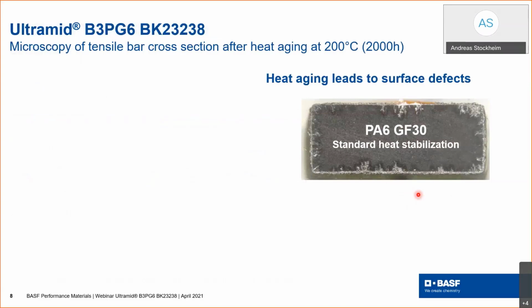How do the stabilization systems work? So therefore, we were looking at the surface of different stabilization systems. As you can see here, the surface defects after heat aging at 200 degrees C, which is very high, after 2000 hours, you see the surface defects on a standard PA6 GF30 with a standard heat stabilization.